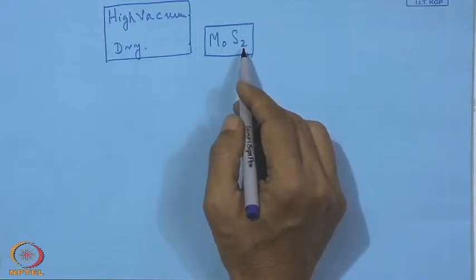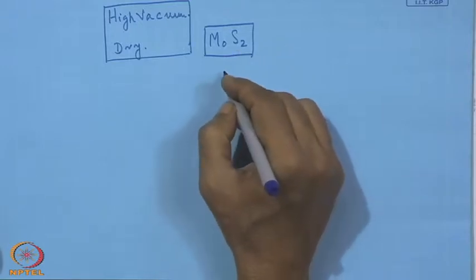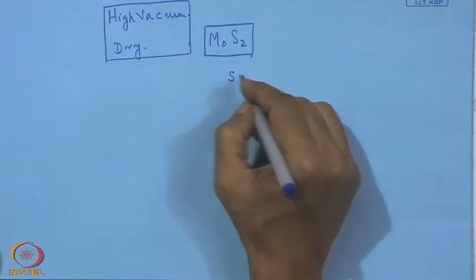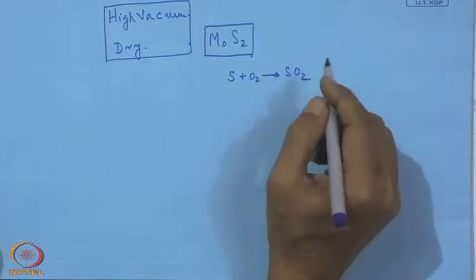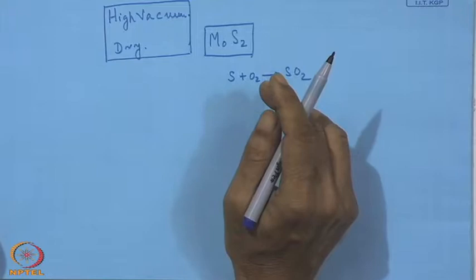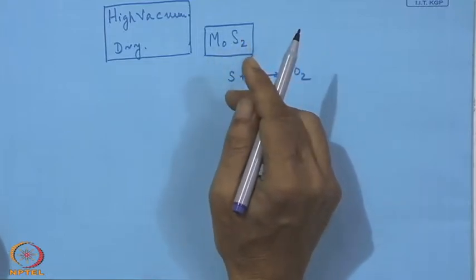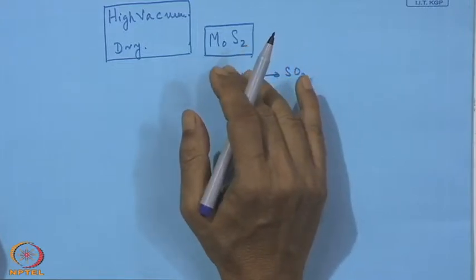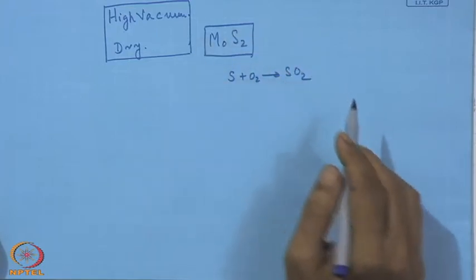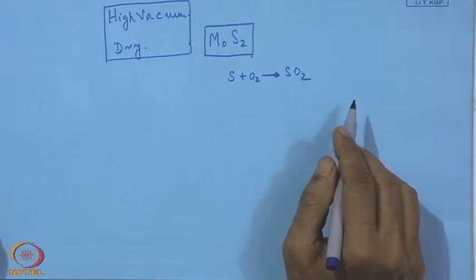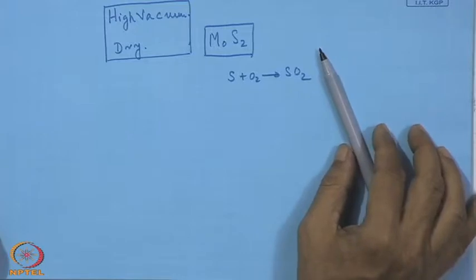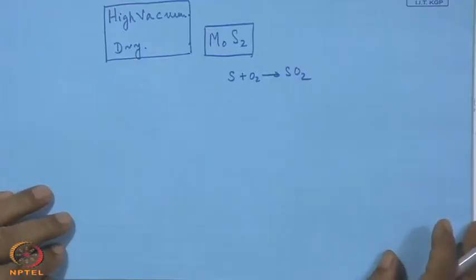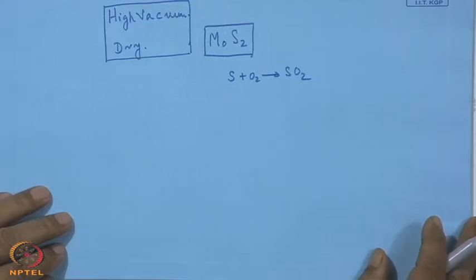That means it will simply absorb moisture and then oxygen will be active and this sulfur will be attacked, and S with O2 will lead to sulfur oxide. So, oxygen will convert this sulfur into sulfur oxide, or it can go inside and also make molybdenum oxide. There is a lot of investigation and documentation on this particular subject. Whatever may be the thing, ultimately it is the total failure of the coating. So, what we would like to say here is that MoS2 alone can be a good candidate for such high vacuum or dry environment, but for mass scale use in numerous mechanical applications, MoS2 alone cannot serve as a good candidate and good coating material.